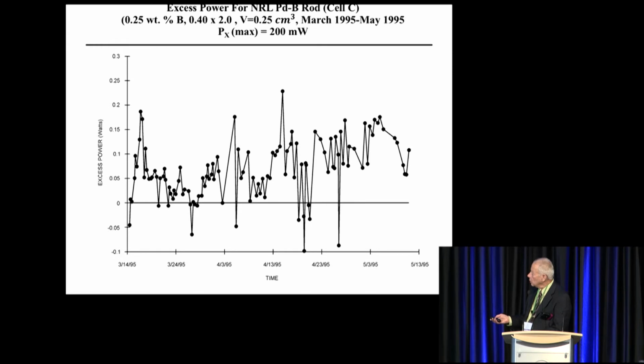In another experiment, almost every experiment, but this is the lower weight percent. This is 0.25 weight percent. And the ones I showed previously, some of those were 0.50 weight percent. We started off with 0.75 weight percent. Now, you might not think that's very much boron, but if you do a calculation, boron is not a very heavy atom. And if you do it by atom percent, you find out at 0.75 weight percent, there is one boron atom for every 15 palladium atoms. So on an atom to atom ratio, it is a fairly significant amount of boron.